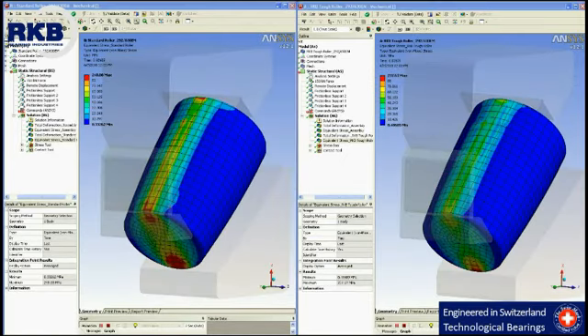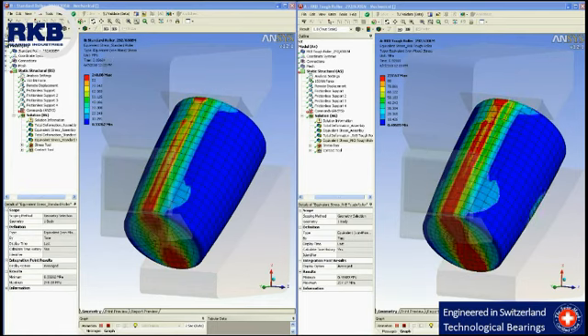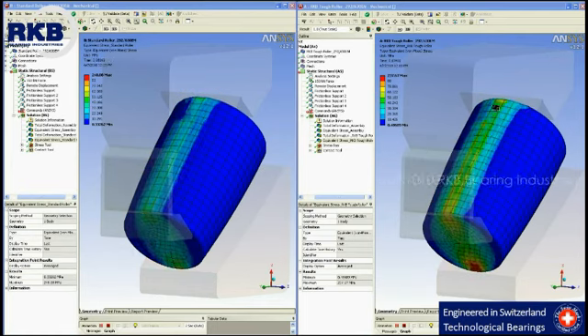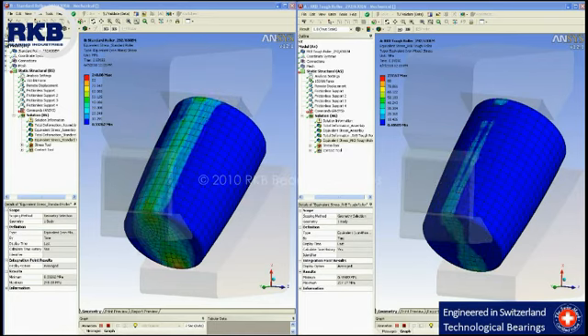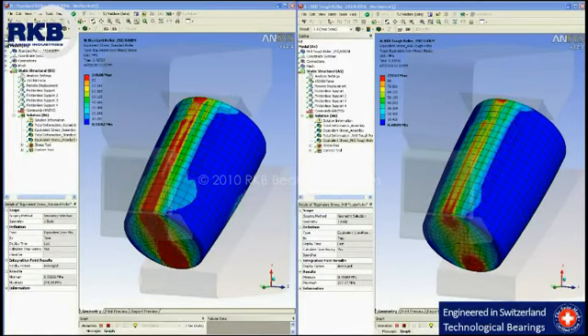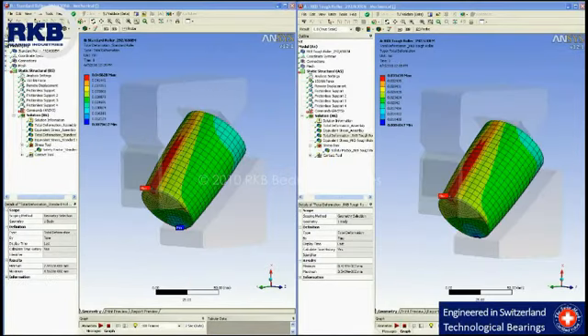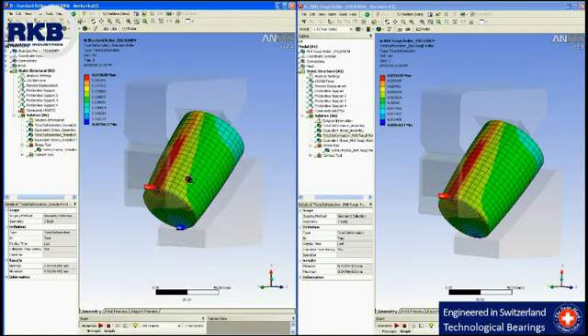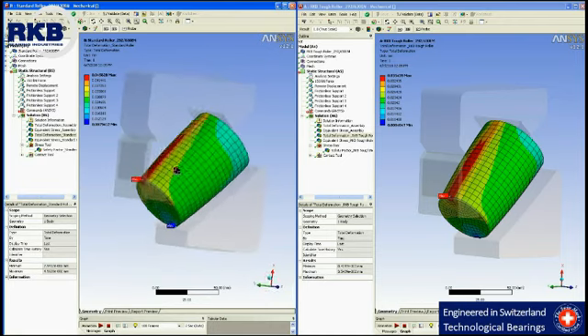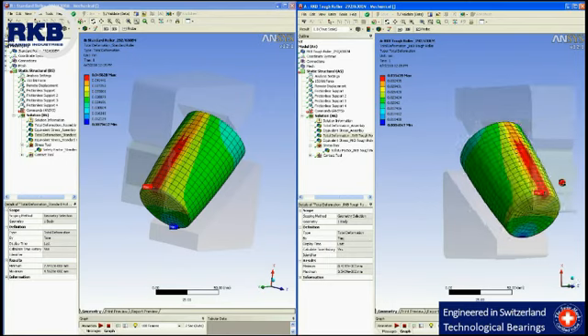For a better understanding of the stress distribution in the rollers, we show simulations for both standard type and RKB type. The main differences between the RKB Tough Roller and the standard roller lie in total deformation and safety factor, because the steel used by RKB has better mechanical properties such as Young modulus, Poisson ratio, tensile yield strength, compressive yield strength and ultimate yield strength than standard steel has. Therefore, as is evident from these graphs, the total deformation is higher in the standard roller than in the RKB Tough Roller,